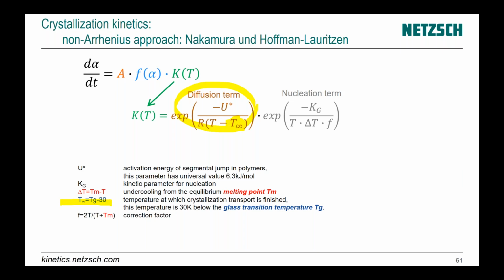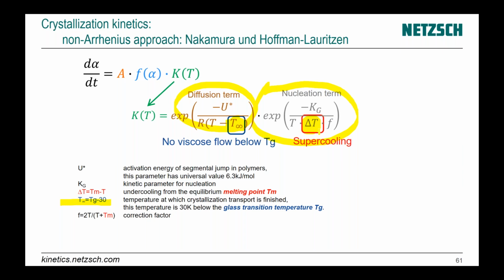It describes how crystallization goes in the glass transition range. The second is the nucleation term, which works in the range of melting and depends on supercooling - the difference between melting temperature and the current temperature. This method works between glass transition and melting.